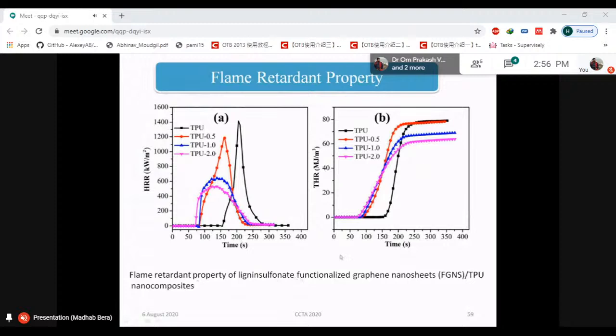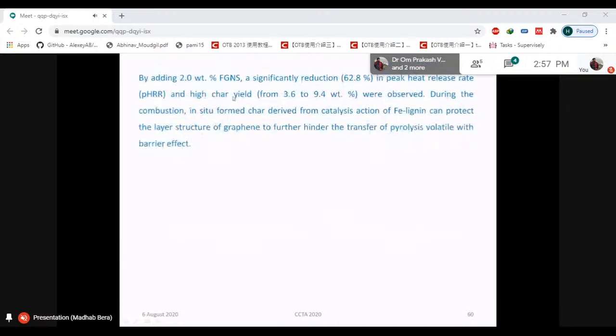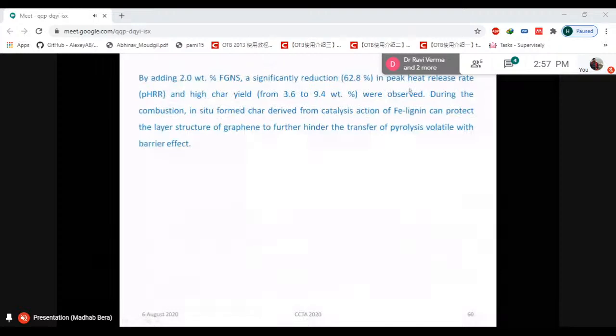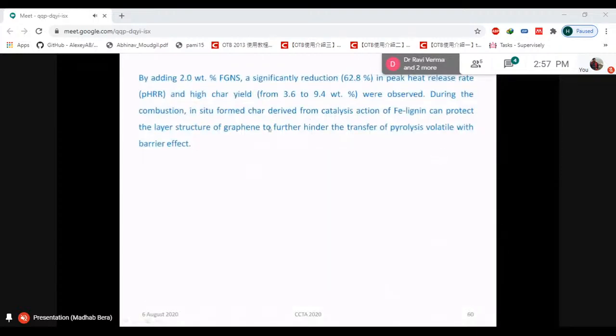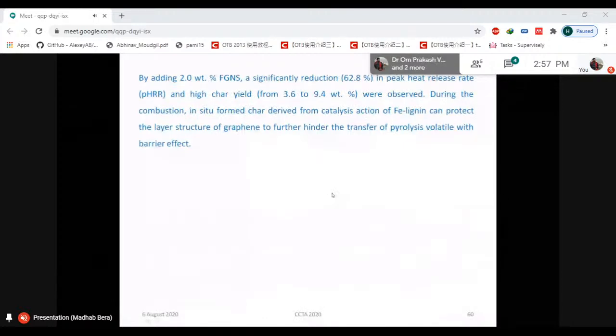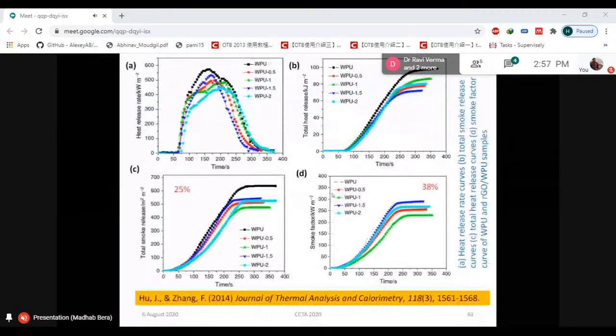The flame retardancy of materials, also thermoplastic polyurethane, can be improved with the incorporation of functionalized graphene sheet. Here, the lignin sulfonate functionalized graphene nanosheet was incorporated into the polyurethane matrix, and it was found that the total heat release rate is decreasing with increasing loading of functionalized graphene nanosheet. By adding 2% functionalized graphene sheet, a significant reduction, 62.8% in peak heat release rate, and high char yield were observed. During the combustion, in situ formed char, derived from the catalyst action, acts as a barrier, and because of that it hinders the release of heat, and heat release rate decreases.